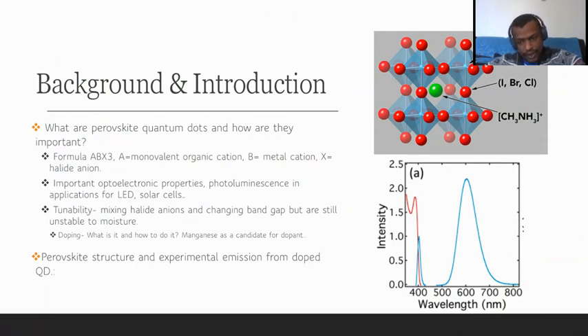And at the bottom right, you can see emissions. This is a photoluminescence spectrum for doped lead halide perovskite quantum dots. And we can see two peaks in blue, because the red one is the absorption. And we're going to focus only on the blue one, so the emission. And we can see the two peaks, the first one around 400 nanometers, which was measured experimentally. And that peak represents the emission from the perovskite quantum dot. And the second peak around 600 nanometers represents the emission coming from the manganese. Next slide, please.